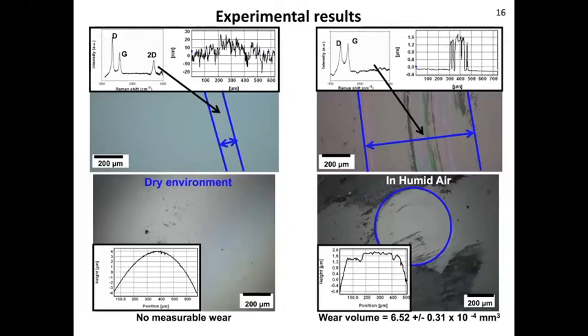And in the wear analysis, that's what we actually observed in the case of the dry environment for our graphene plus diamond solution: the wear was almost undetectable. This is the wear track analysis. You see just some oscillations due to the roughness profile. In the case of the ball counterpart, we see some compression, which is caused by the Hertzian contact pressure when you apply the load during the sliding. So this is not the actual wear of the surfaces, but rather changes in the surface due to the applied load.